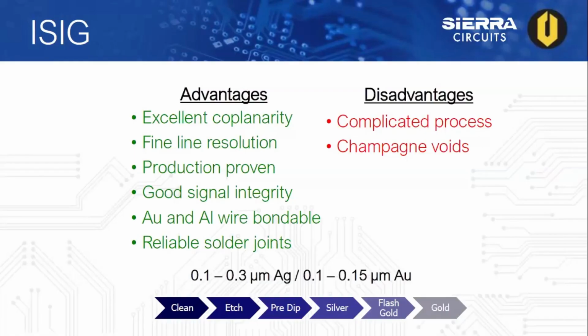Now these thicknesses are what have been tested with ISIG, which ranges from 0.1 to 0.3 microns of silver and 0.1 to 0.15 microns of gold.